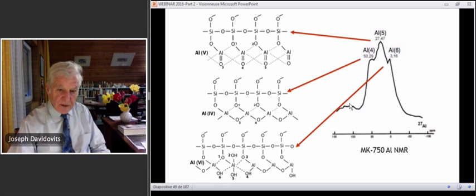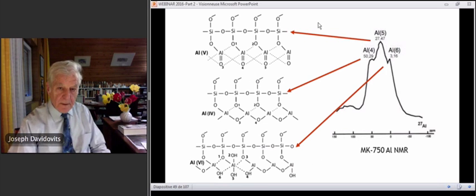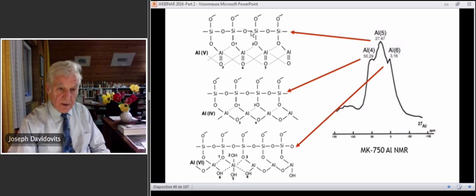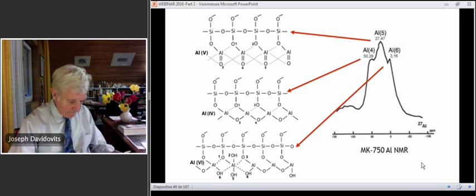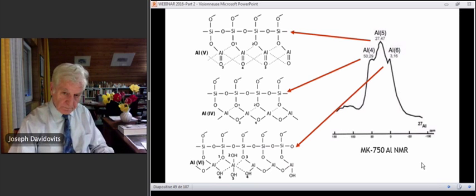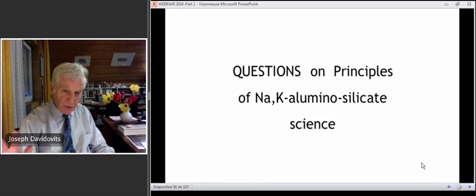And depending on how the metakaolin was calcined, depending on the nature of the clay, you may have a different amount of these 3 reactive molecules, and sometimes the OH is relatively high. It can be between 10% by weight and 30% by weight. Is it too complicated for you?